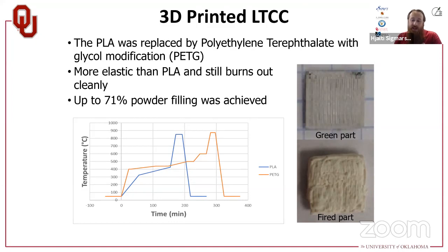So that was actually quite exciting, being able to print out of a $1,000 printer a ceramic part. And this is just a graph showing the different profiles that we use. We have to slightly adjust our profile for doing the sintering for the PETG. We just needed to do a little bigger dwell for it to remove all the particles, and remove it a little bit slower.